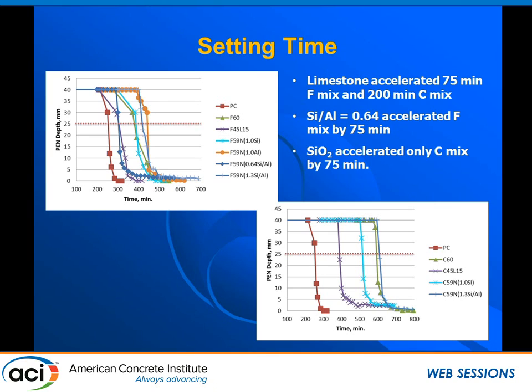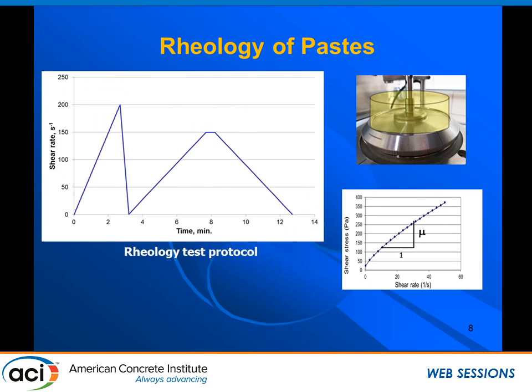We have for the F mix a 75-minute acceleration, and for the C mix a 200-minute acceleration. We have another mix that accelerated the setting, the 0.64 silica to alumina ratio, shown here in blue. All the other nanoparticles for F either did not accelerate setting or even delayed it slightly. For the C fly ash, the Nano Silica accelerated slightly, but not as well as the limestone.